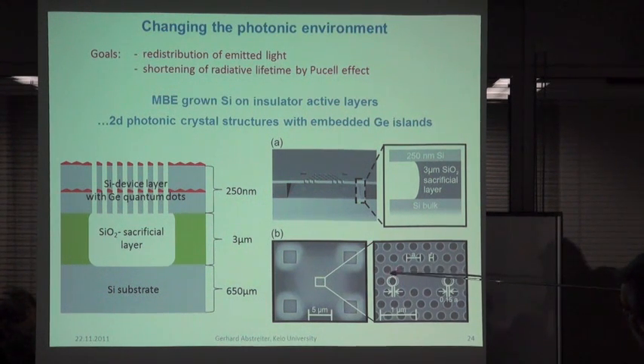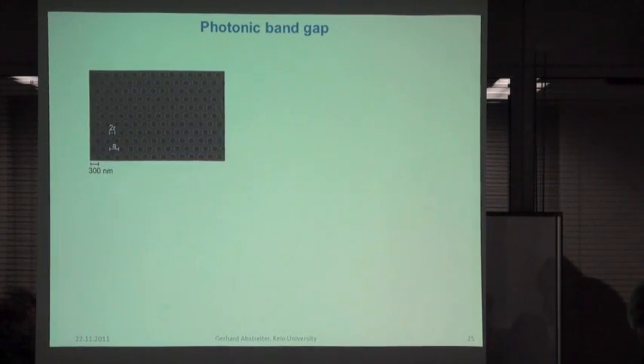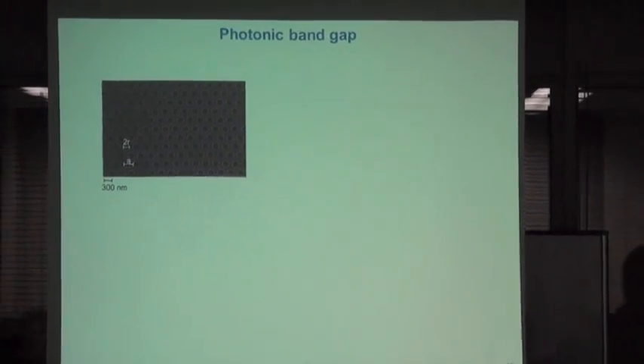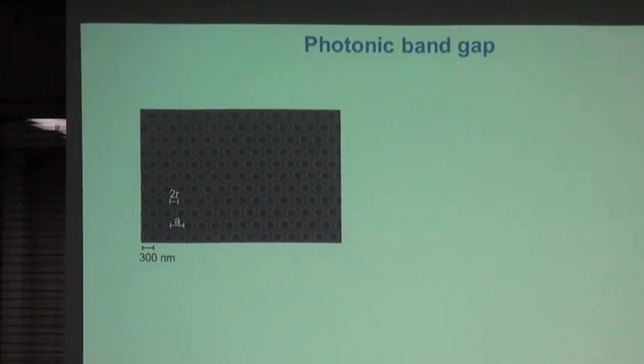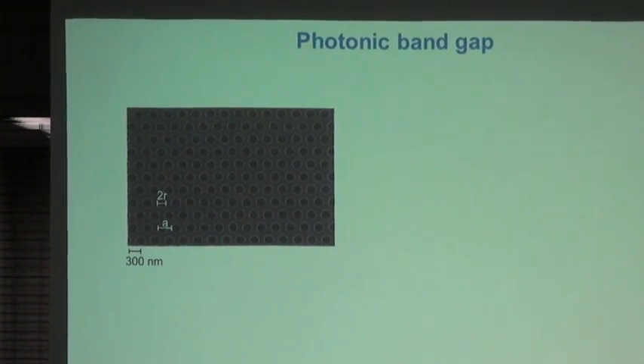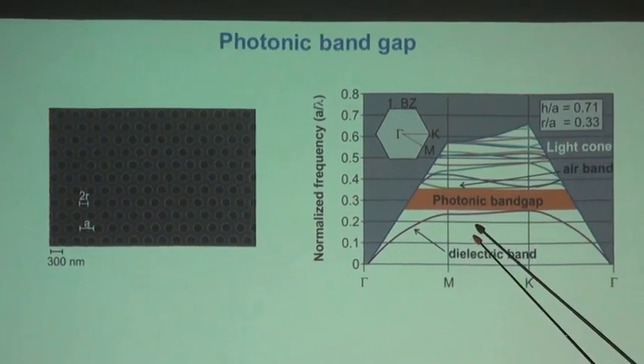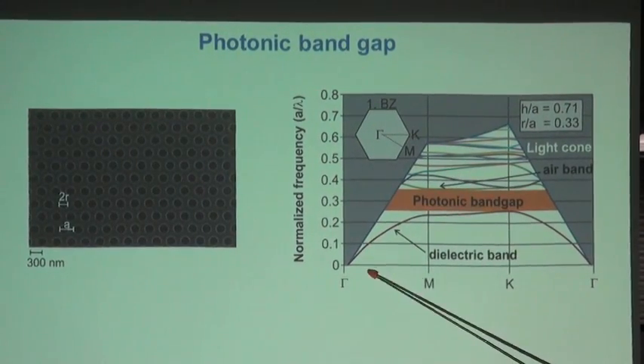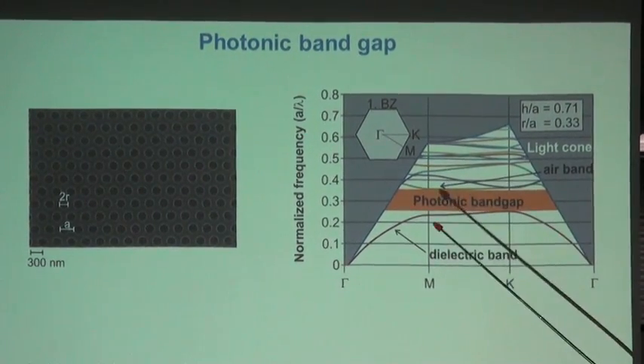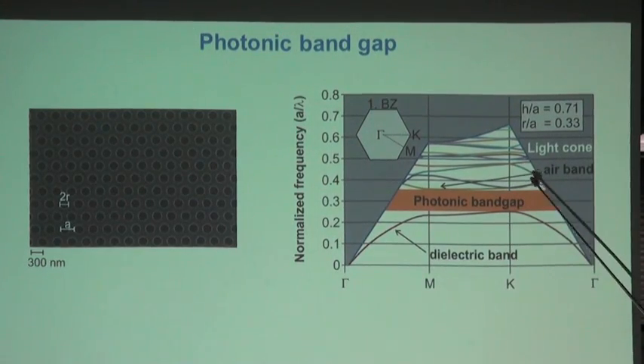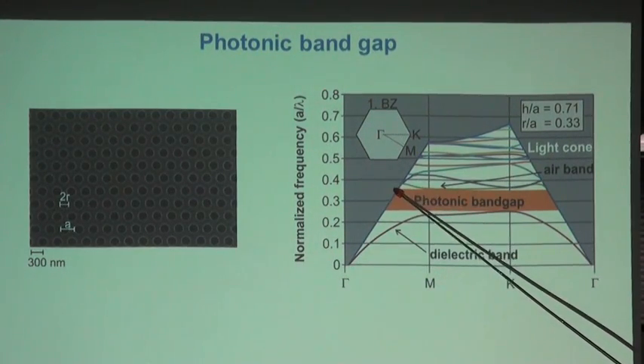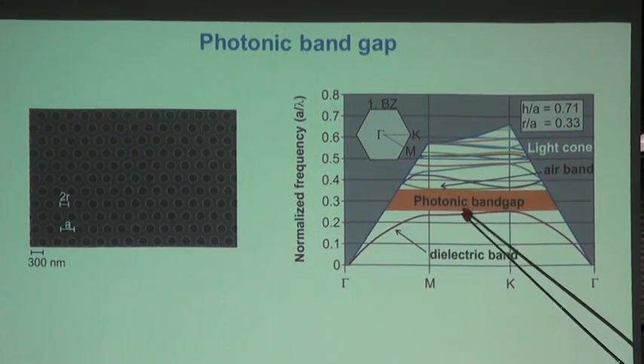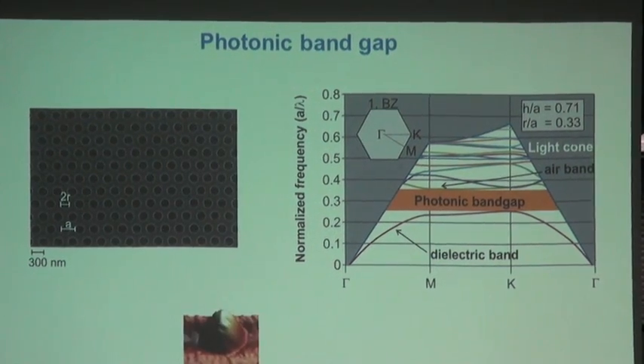And you can also make a resonator, a defect, which shifts the holes, and then you get modes. So what you get in such a crystal is a two-dimensional photonic crystal, so it's a periodic variation of air and silicon. These are just holes punched through this silicon membrane, so it's a freestanding membrane. If you look at the photonic properties of this, this is a light cone, so the dispersion of photons is linear, and then due to this periodic structure we get this photonic band gap. So here, no photons can be, let's say, emitted in this direction, in this field.